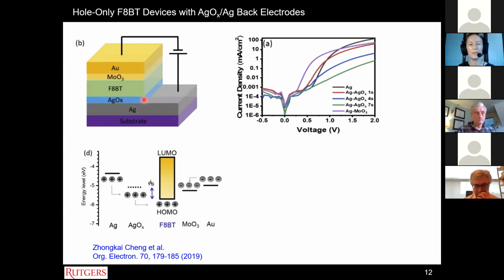We actually did a previous study where we looked at the thickness of these oxides, and for 1 second, they're less than 5 nanometers in thickness. And you can see from the device behavior that the shorter exposure time, 1 second, produces the lowest turn on voltage and has a high current density, almost as good as that of a silver MoO3 interface. So you can say that the oxide is functioning almost as well as MoO3, but we don't have to do that additional deposition step.